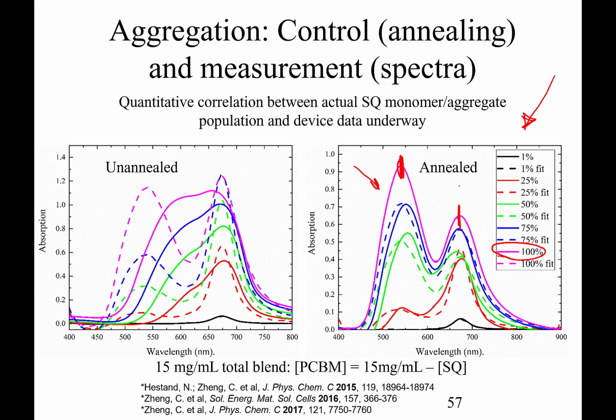At the same time, whether we look at annealed or unannealed, we see when we have a 1% squaraine sample, that means the squaraine is surrounded by PCBM. It's effectively a solid solution. And what we see here is this peak at about 675 nanometers. That's a single peak. And the idea here is we can mix these together. We can fit all the spectra in between.